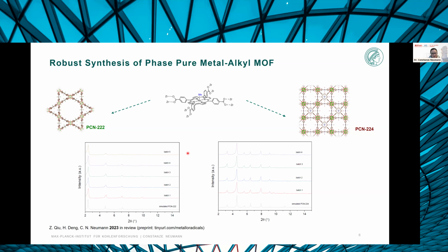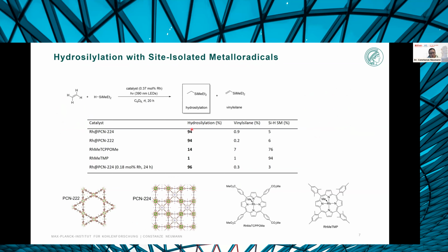And with that compound in hand, we were interested to see if we could use light, so in this case 390 nanometer light, to split the rhodium carbon bond in the rhodium methyl precursor in order to access the rhodium-2 metalloradical, and if that metalloradical would then be able to carry out catalysis. So the rhodium-2 in PCN222 and 224 was indeed able to furnish the hydrosilylation product very efficiently. And when we look at the molecular model system in solution, that would correspond to the linker that we're using in the MOF, we only got 14% yield under the same reaction conditions.